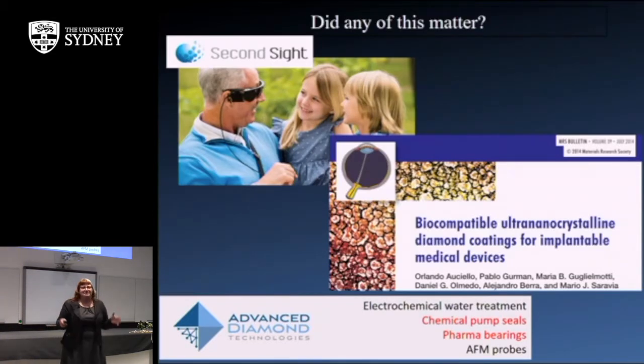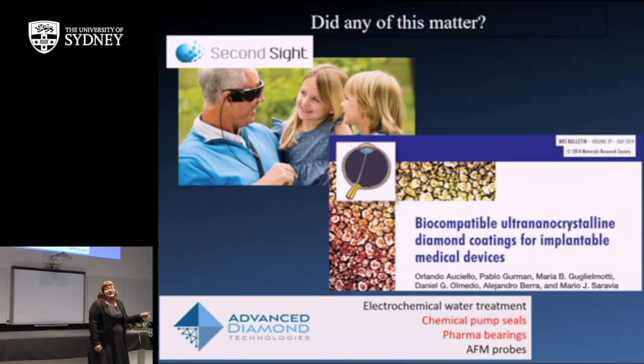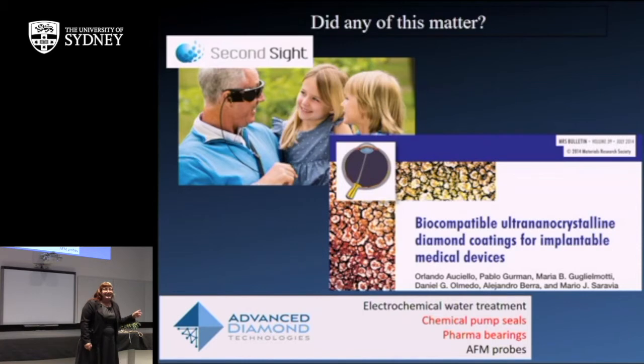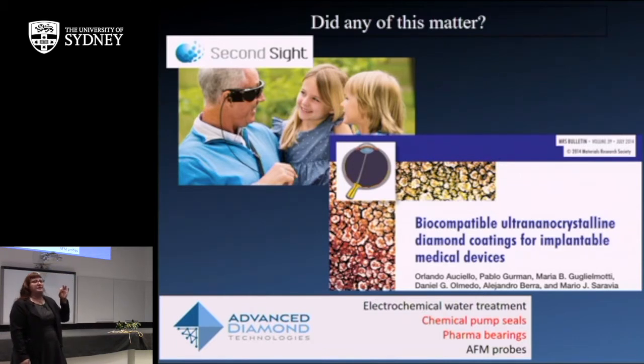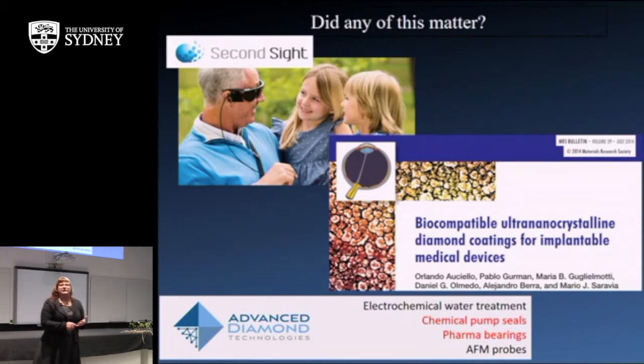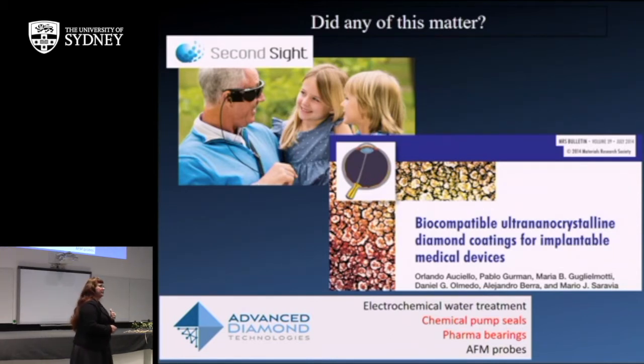So did any of this matter? Well, I think the people that are starting to get retinal implants so that they can see again care. And one of the reasons why that's possible is because these things are coated with these diamond films. If you try to put silicon chips in somebody's eye, they last like 2 weeks. The body is actually an extremely corrosive and difficult place for semiconductors to live. You need a material that's extremely bioinert to be able to do this. And you need materials that are also electrically conductive. So these types of diamond films are actually extremely useful for bioimplants.